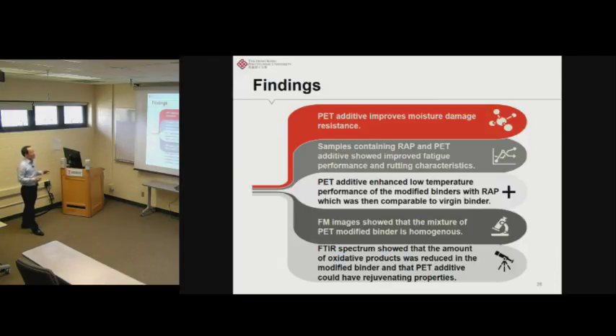Here is a quick summary of the findings we have obtained so far. First of all, through the chemical treatment process, we converted our waste PET material into PET additive, and we found the PET additive can significantly improve the moisture damage resistance and can serve as an anti-stripping additive. Also, if we use the PET additive, the rutting performance is not changing much, but we can significantly improve the fatigue performance of the binder and the RAP binder.